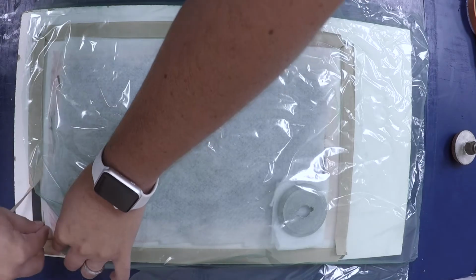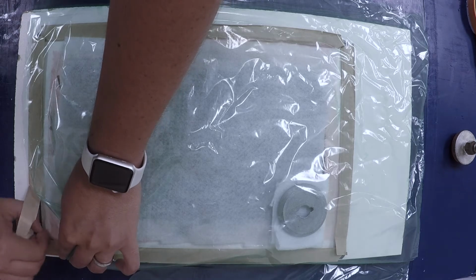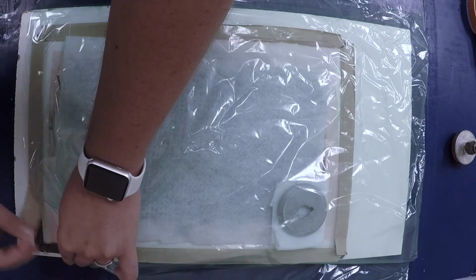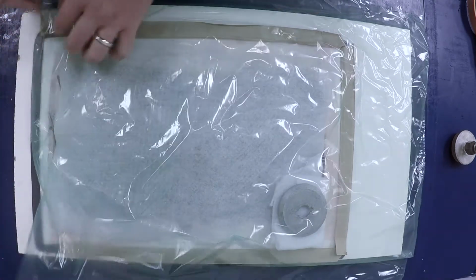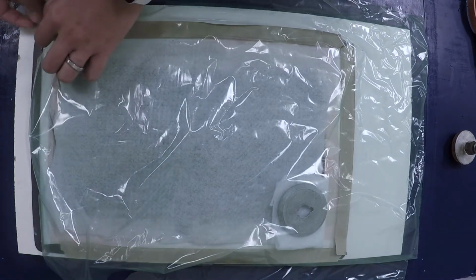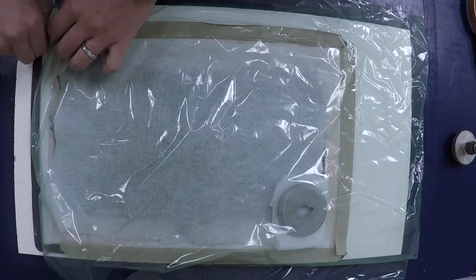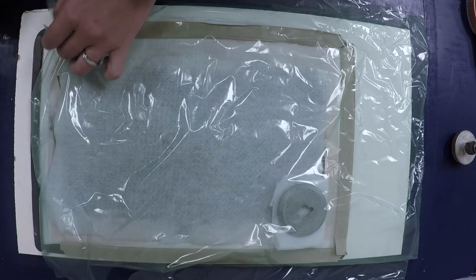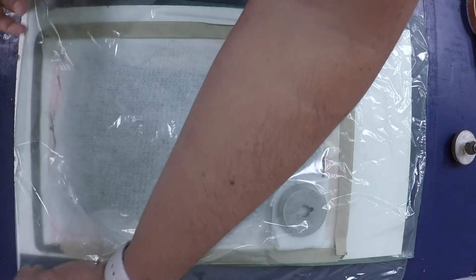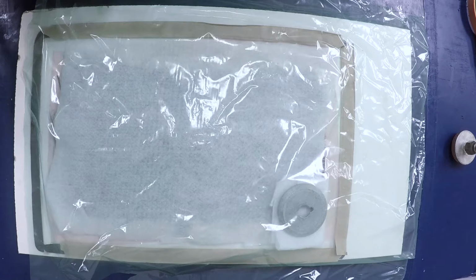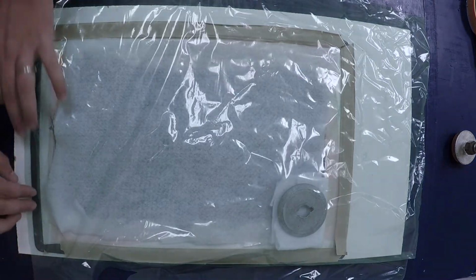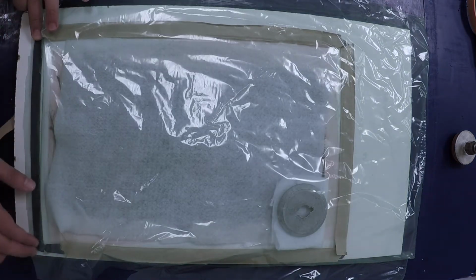Having placed all your films, you may now begin to stick the vacuum bag onto the tacky tape. Begin by peeling one side of the tape and sticking the bag as close to the edge as possible. After this, you can move around the mold as you see fit. In this case, I will stick both sides of the bag first, and then close the last side opposite to the first side.